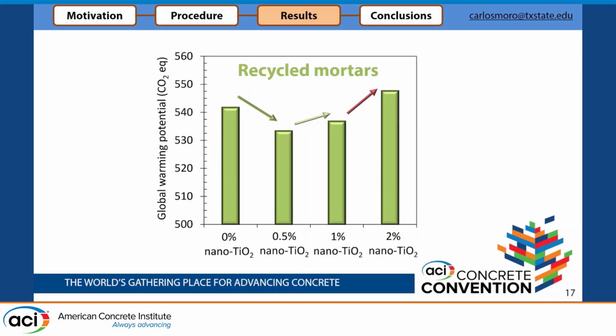And again, this is a recycled fine aggregate that usually is the part of the recycled aggregate that people don't like, because there is more residual mortar stuck in it. In this case, we see the reduction of the CO2 emissions per cubic meter of mortar compared to the reference sample. That means that we have 3 groups, depending on the percentage of recycled aggregate that we have, and we are always comparing with the reference one with no nanoparticles. That means that the red column is basically 0% recycled aggregate, and we are comparing with 0% recycled aggregate. The green one, we are comparing with 100% recycled aggregate all the time.